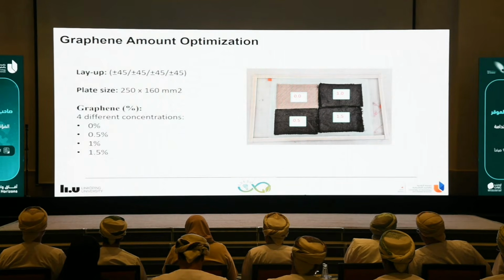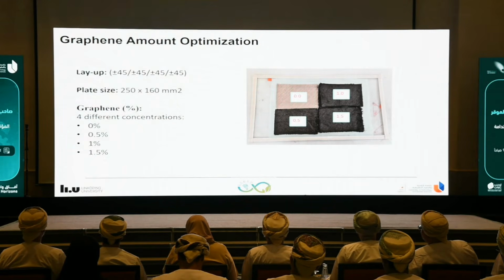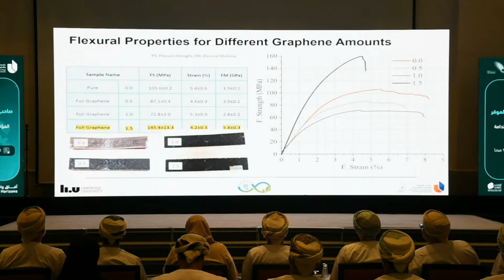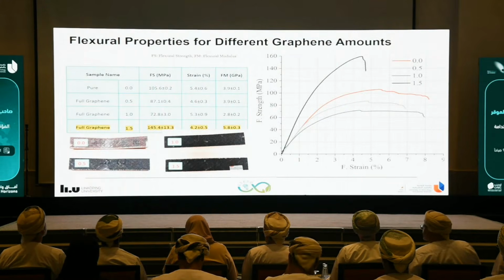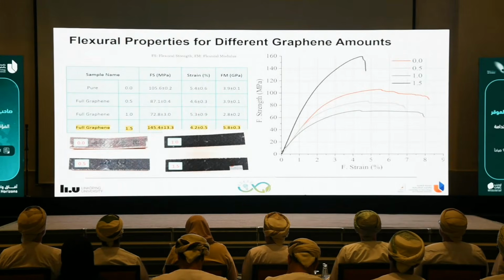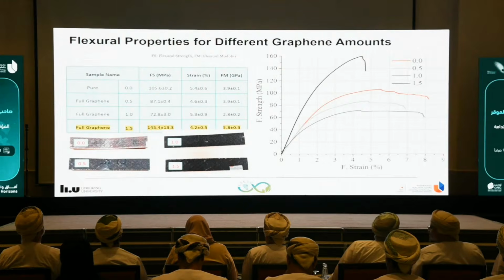So when they did coating for the first time, they used a certain concentration that they use for thermal conductivity and not for natural fibers. So the results were different. What I am showing there is the strength of the material as a function of the strain. And as you can see, at 1.5%, we have a very good improvement of the properties.